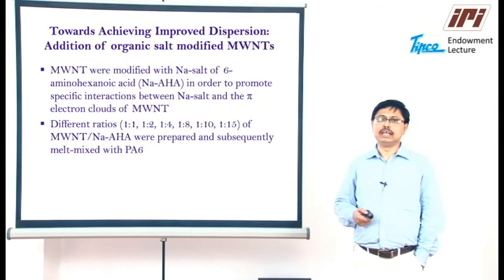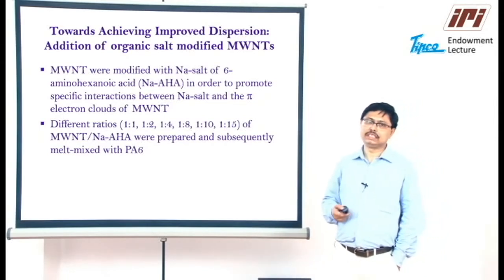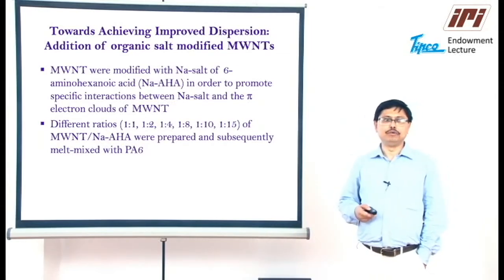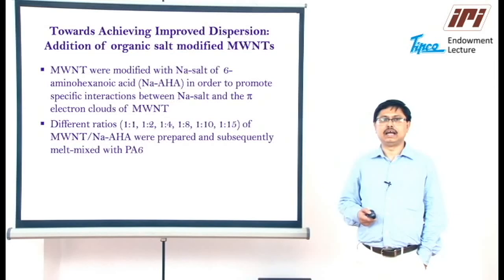In order to improve the dispersion, we utilized a novel organic modifier, where the sodium salt of 6-aminohexanoic acid is employed to modify the carbon nanotubes through an aqueous medium, and the process will be discussed shortly.